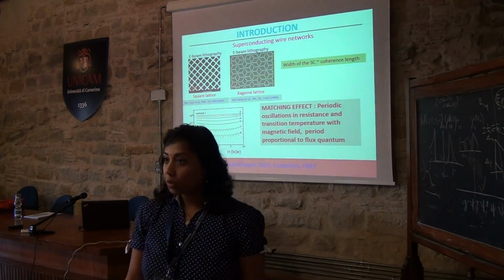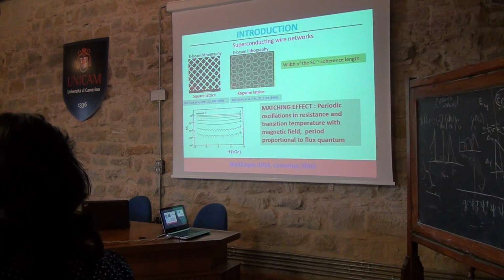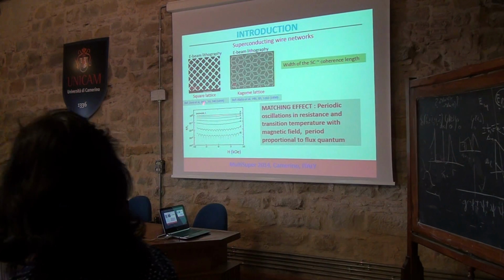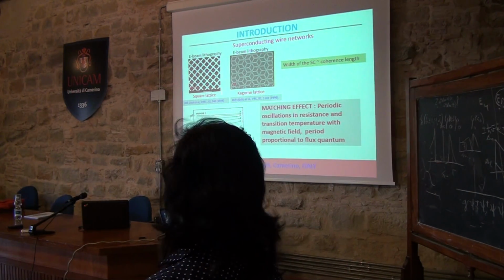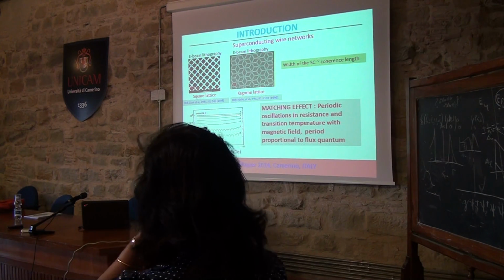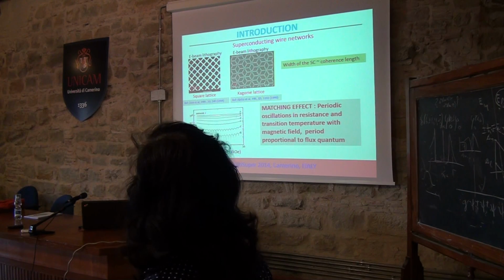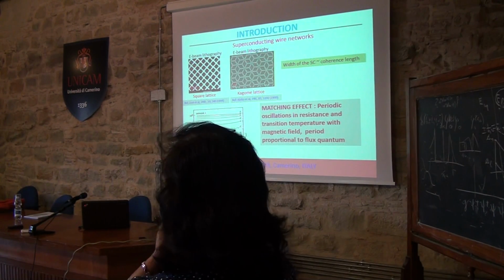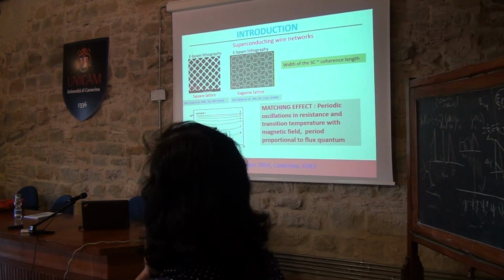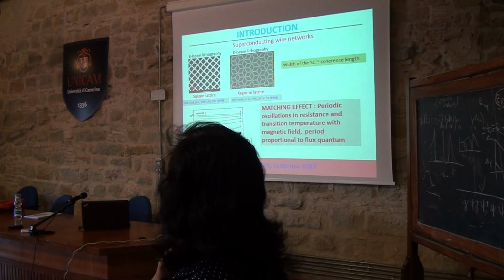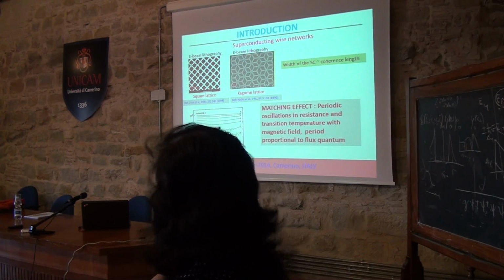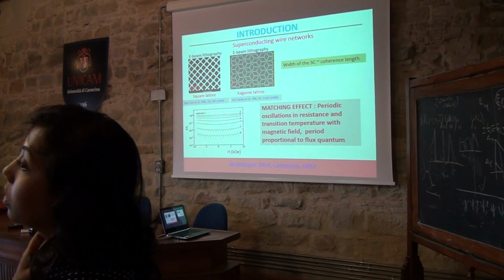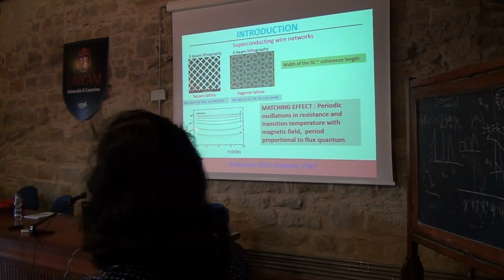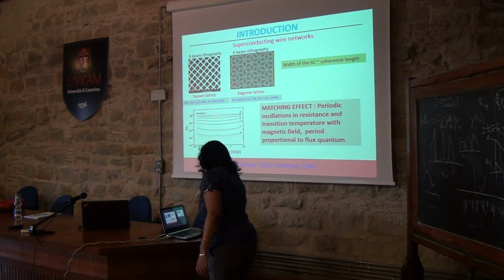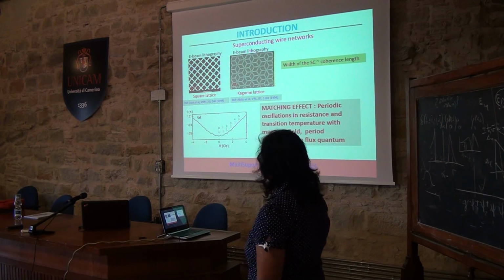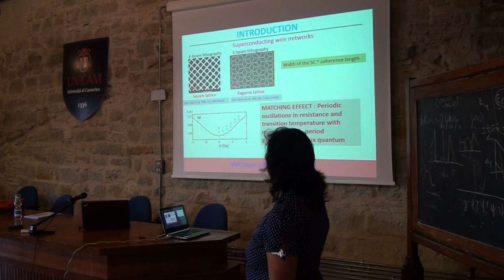Okay. When we talk about matching effects, the first observation of matching effects was seen in superconducting wire networks. They were done in different geometries, either square lattices or Kagome lattices. The essential point is that the width of the superconductor was of the order of the coherence length. What was observed is that if you make a resistance measurement of these wire networks as a function of magnetic field, you start observing oscillations in the resistance. The period of these oscillations is proportional to a flux quantum, and this is what was referred to as the matching effect. In addition, you also see oscillations in Tc. However, this is a very, very small effect.